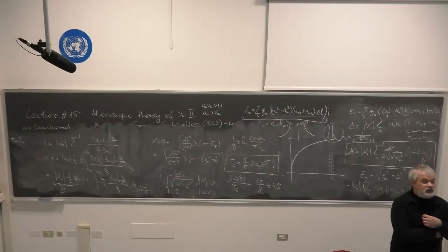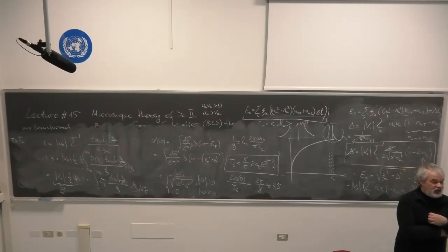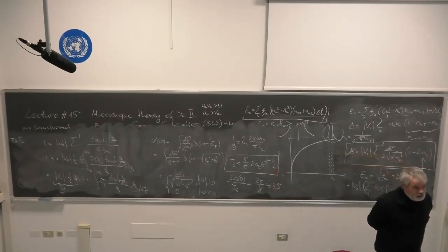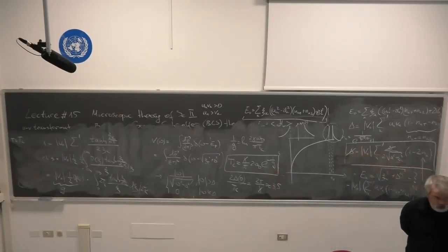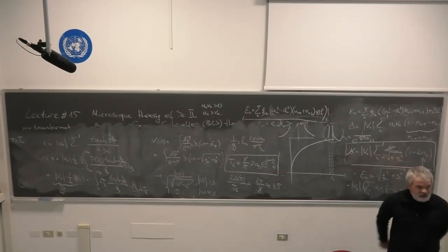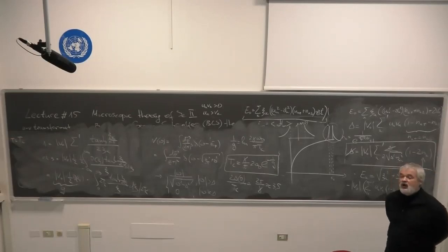You need to deal with the Feynman diagrams and Green functions. By the way, everything that I did here referred to the so-called weak coupling. I assume that my coupling constant is pretty small, and both the gap and the critical temperature are much smaller compared to the Debye frequency. If you have G very large, in principle, the theory which I present to you is not correct.